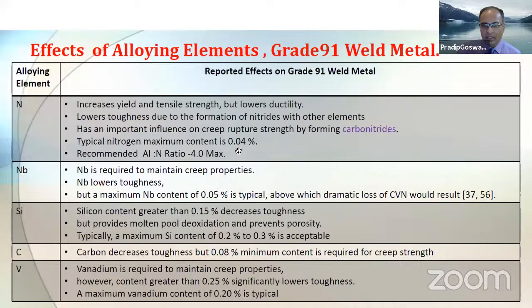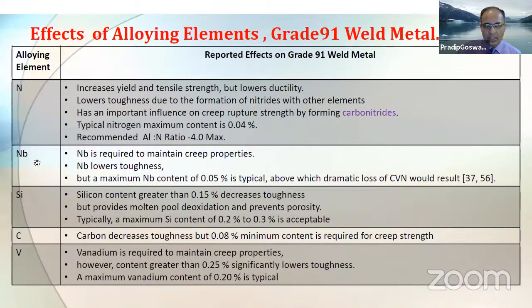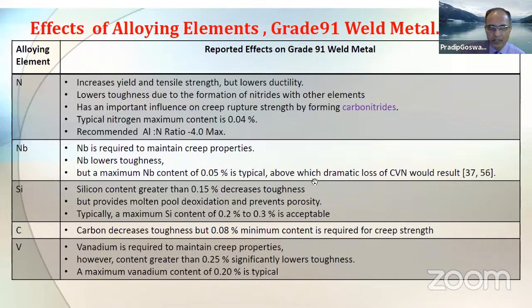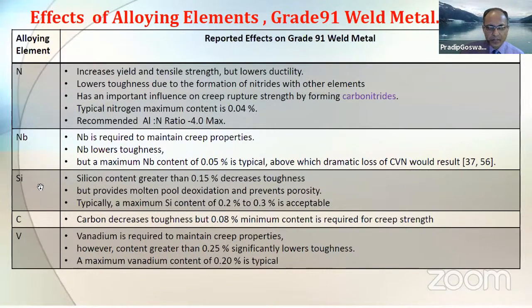Typical nitrogen content allowed is 0.04%, and the recommended aluminum to nitrogen ratio is around 4 maximum. Now, next is niobium. Niobium is needed to maintain the creep properties. It lowers toughness though, but that's why the maximum niobium content is approximately 0.05% typical, and generally above that there's a dramatic loss of Charpy-Notch test values.